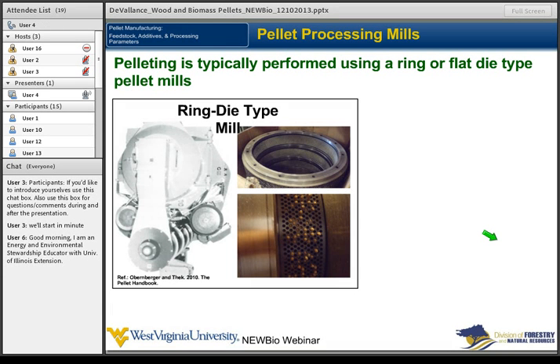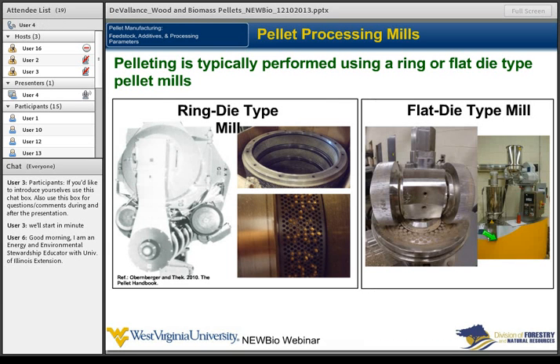Okay, so we move through these pre-treatment processes and look at the type of pelleting that we typically see. In general, there are two common types of pellet mills, a ring and a flat die type. The ring die type is probably the more common industrial one, and that's over here. So we have this ring inside this machine, then you have a set of rollers that are going around while the die is also turning, and the feedstock's getting pushed through these dies and comes out and gets cut off. So that's the ring die type.